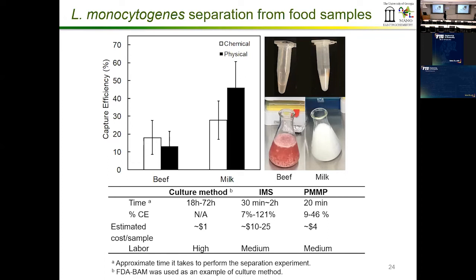So, this is about 20 minutes compared to the 18 to 72 hours needed for the culture method. And estimated cost is around $4 per sample. And the capture efficiency we got was anywhere from 9 to 46. It's not really high. Here in the culture method, it's not captured because it's enrichment, so you don't really worry about capture there because you're growing the cells.